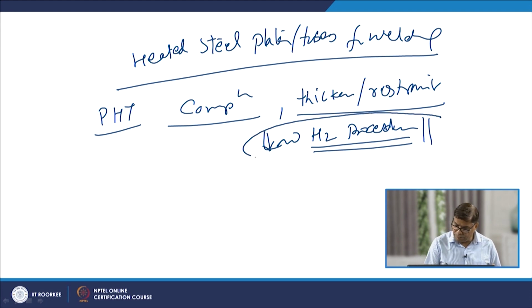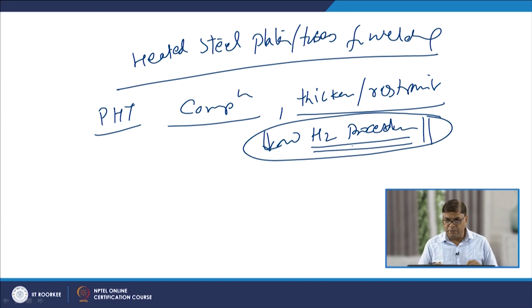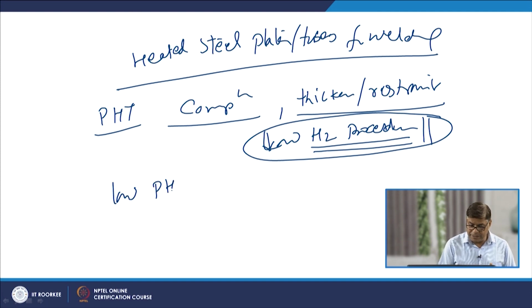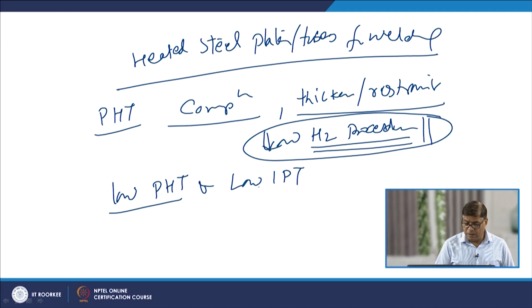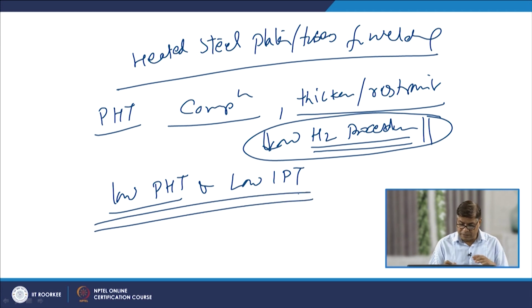So if we are following the low hydrogen procedures, then our requirement for preheat is also reduced. So that will allow us to use the lower preheat temperature and the lower interpass temperature. It is always desired that whatever preheat temperature is used, a similar interpass temperature is also maintained for uniformity of the structure at the different layers, so that all zones during the welding in multi-pass welding will be experiencing similar kind of metallurgical